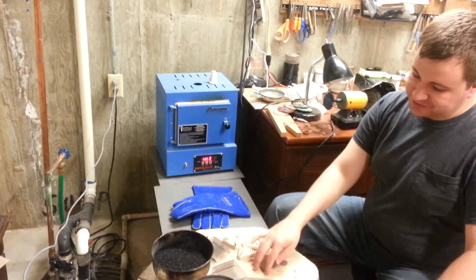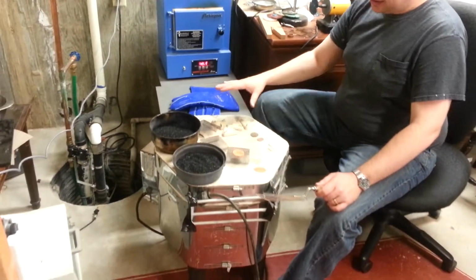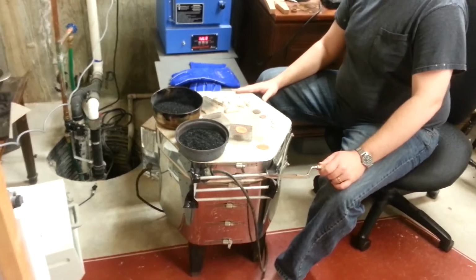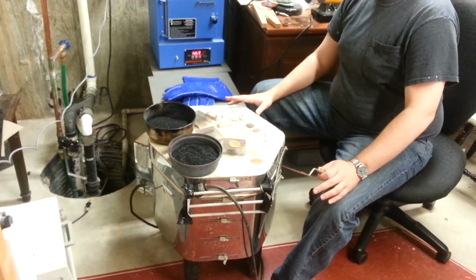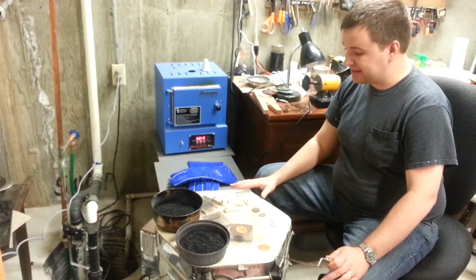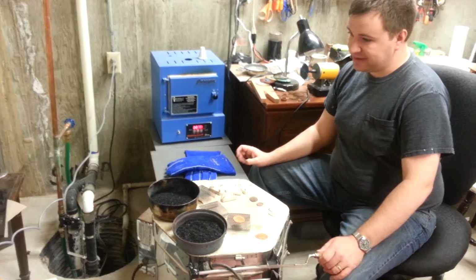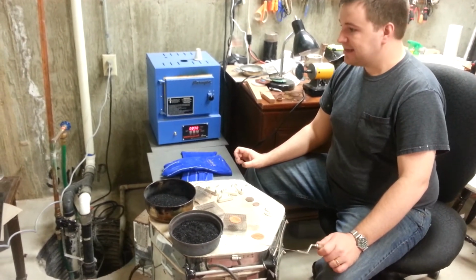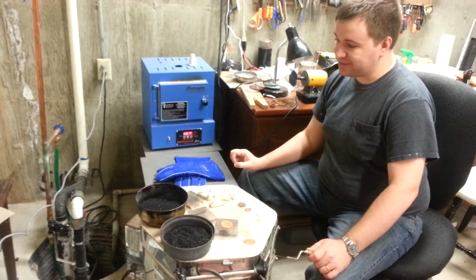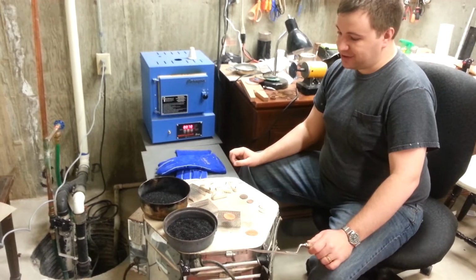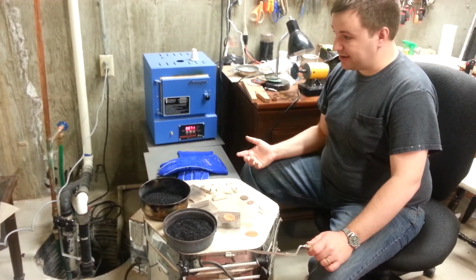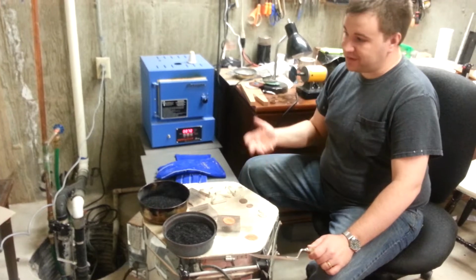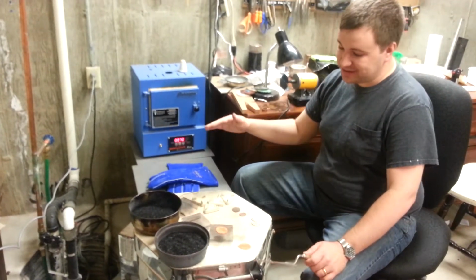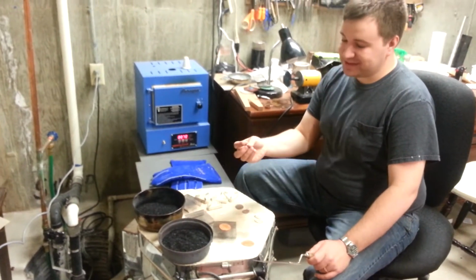This kiln for ceramics that everything's sitting on is a possible way of doing it, and I have successfully fired metal clay in these kilns. The trick is regulating the temperature, because if you don't know exactly what temperature you're dealing with, you can go either too hot, which has generally been what I've done, or not hot enough for long enough at a consistent temperature, and you'll end up with cracked pieces or pieces with bubbles in it.